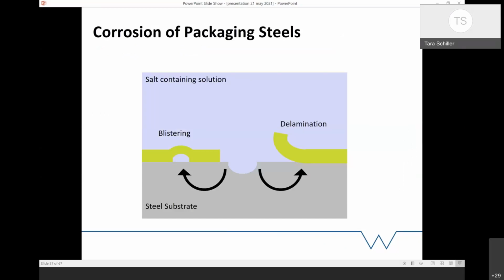But yeah, so if you've got the substrate and you start getting any blistering, this same effect happens with plastics. When we look at, say, polyester boats, we get an osmotic blistering happening on that sort of thing. So if you've done study to do with polymers and things, I'd probably give that sort of an analogy where the attack comes from different pathways and basically just causes catastrophic failure a lot of the time. And in this case, with what Steve's looking at, he's looking at packaging steels for food and stuff.